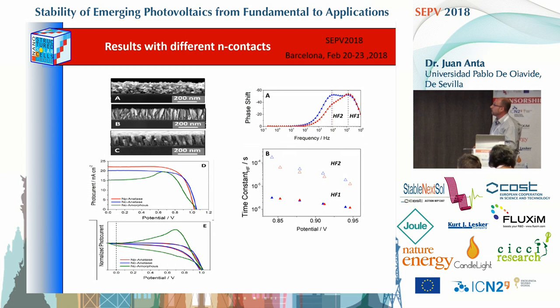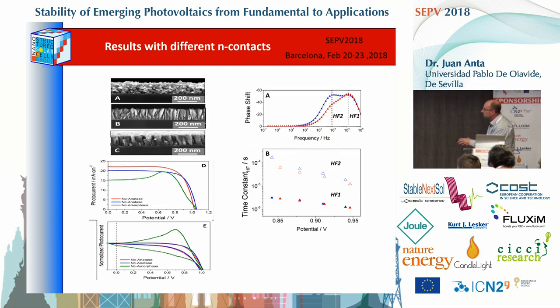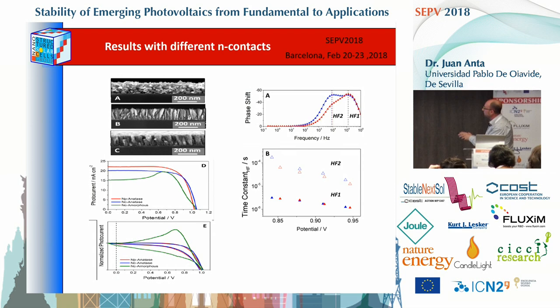We also studied alternative electron-selective contacts, comparing typical mesoporous TiO₂ anatase electrodes with nanocolumnar TiO₂ structures — also crystalline anatase — and with amorphous TiO₂, which is much less conductive than normal anatase. Interestingly, when using amorphous TiO₂ the photocurrent is smaller, but the open-circuit voltage is essentially the same for all three cases, consistent with our hypothesis that the open-circuit voltage is determined only by the bulk of the perovskite itself. However, for these amorphous-TiO₂ devices, we start to observe differences between the blue-light and red-light impedance data, indicating surface-mediated processes occurring in the device.